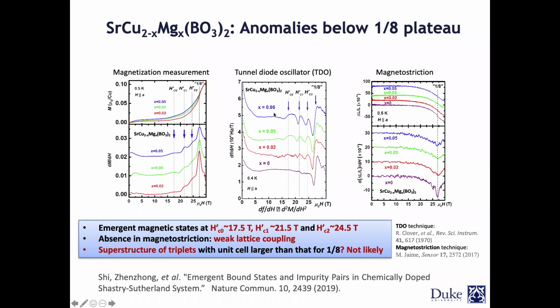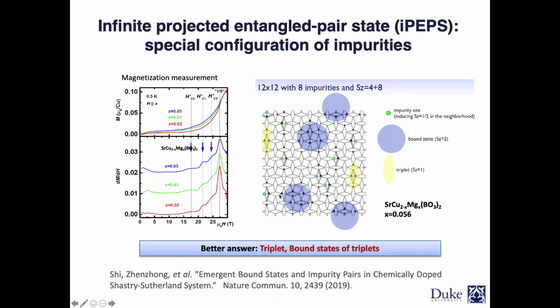In this case, we started to collaborate again with the theorists. If you look at the green dots, these are the impurity sites. We randomly put these impurity sites in, breaking the dimers. Originally, they talked about a bound state of excitations, as a function of field, condensing into the ground state. But here, because we are breaking these dimers, there are going to be special cases where only the triplet, or Sz equals 1, is also present. One of these wiggles is also going to represent that.